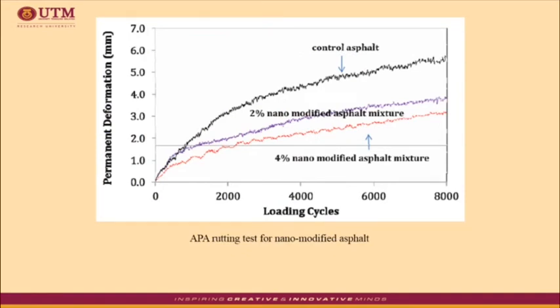Researchers have used nanomaterial modified asphalt and characterized properties such as dynamic modulus, creep, fatigue, and rutting. For example, in this figure, the rutting depth measured using the asphalt pavement analyzer (APA) illustrated that the addition of 2 to 4% nanomaterials by weight of asphalt can reduce the rutting depth by almost half. Furthermore, it was found that the rut depth of nanomaterial modified asphalt mixtures decreased compared to the control mixture, and smaller rutting depth was observed for a greater percentage of nanomaterials in mixtures. This shows a potential improvement in the properties of asphalt mixture.